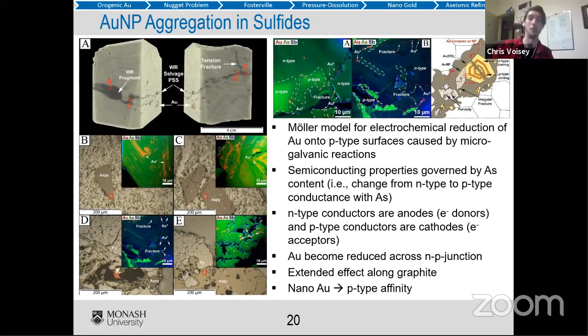The other reason why this is important is that nanoparticles like P-type affinity crystals. That's why there's a lot of studies that show gold nanoparticles stuck to arsenopyrite. It's normally a P-type conductor. So what I've done here is mapped out where arsenic was the highest in these crystals, which would be the P-type domains. And then bits that are not here in the hatch line, these would be N-type domains.